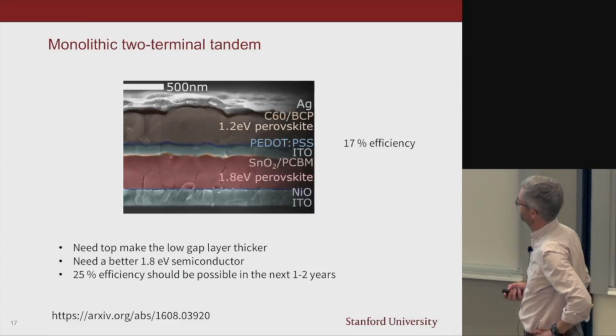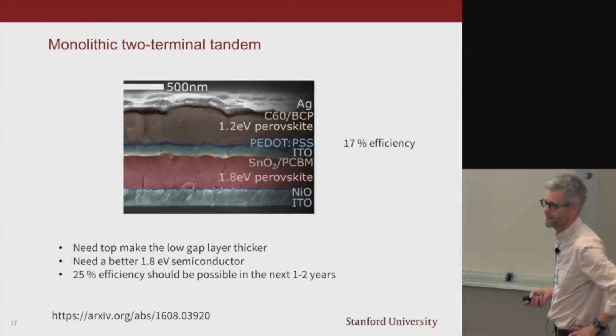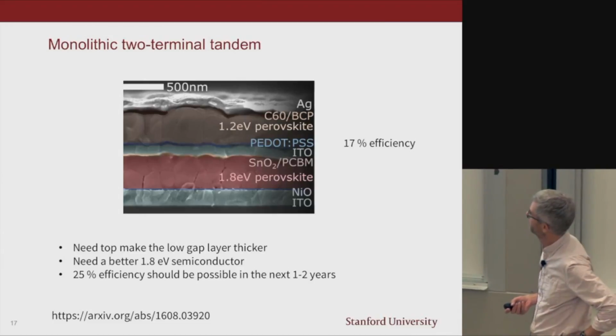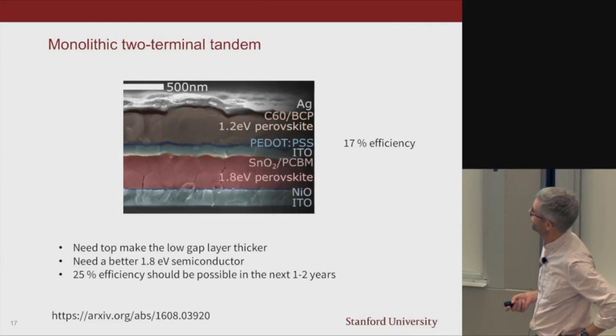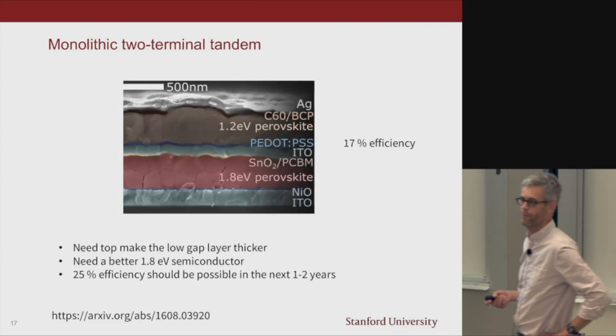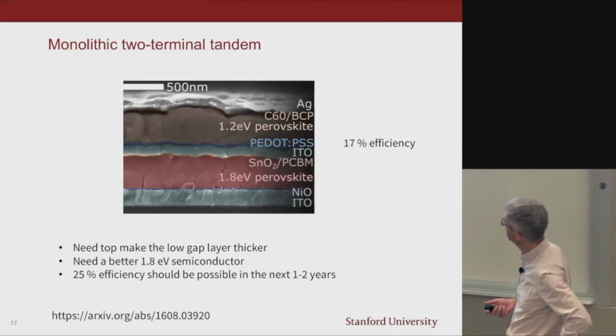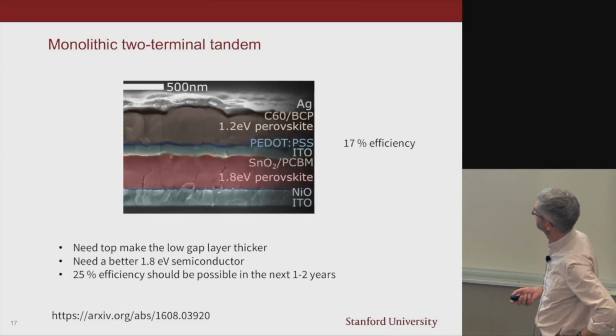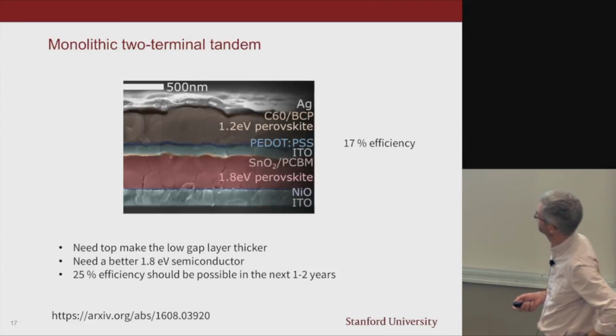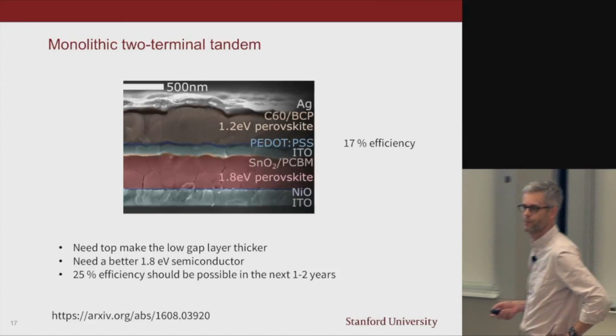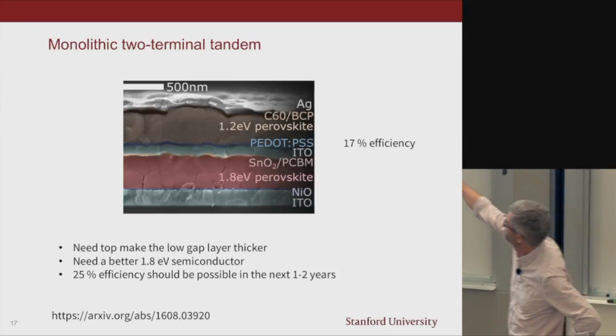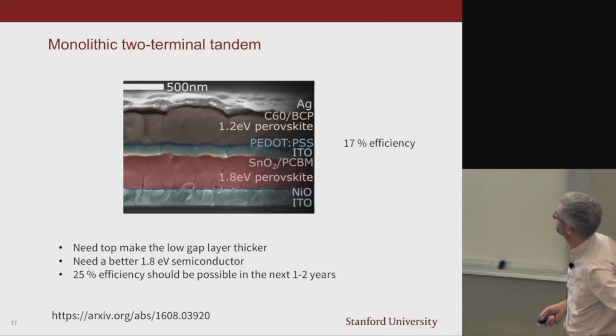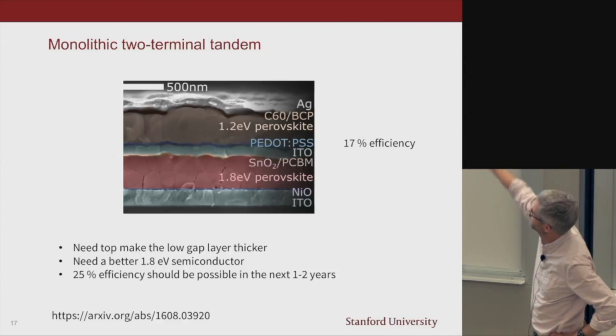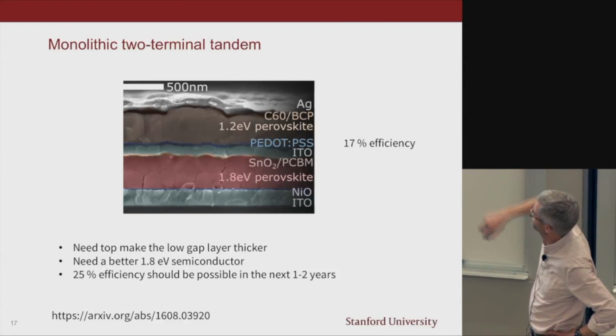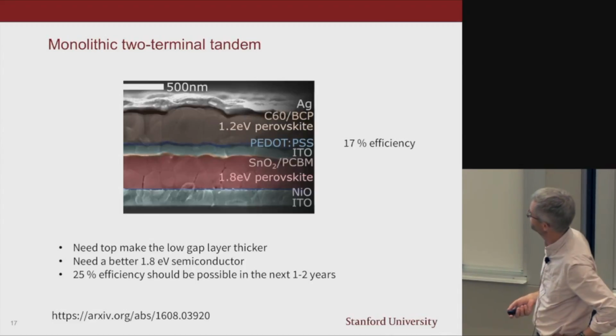Another breakthrough, and I think this is going to be accepted in science this week. We figured out how to do a low band gap perovskite. We sprinkled in a little bit of tin to replace some of the lead. We dropped the band gap down to 1.2 electron volts. And here's a side structure of the first all perovskite tandem.